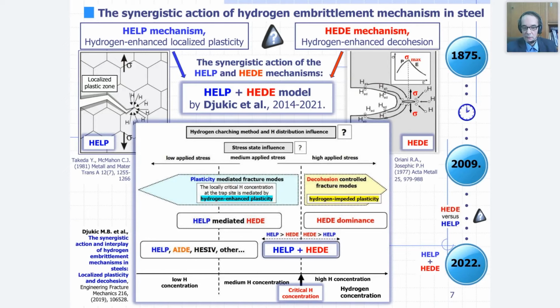At hydrogen concentration on the local level in the material below the critical, which means low or medium hydrogen concentration, we have plasticity mediated fracture modes of the material, which means that the local critical hydrogen concentration at the trap site is mediated by hydrogen enhanced plasticity. So we have a hydrogen plasticity mediated mechanism. HELP is not the only one. We have others proposed, like AIDE, like adsorption, and other mechanisms, and also HELP mediated HEDE,